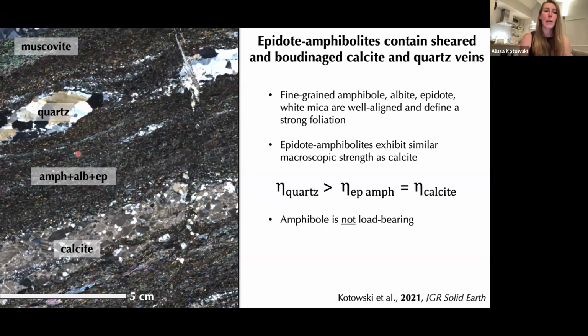So the epidote amphibolite matrix here, we can see that it's exhibiting a similar macroscopic strength to this calcite vein, but it's weaker than this quartz, which is being boudinaged within this foliation. So this allows us to put a bit of a bracket on how strong or weak these epidote amphibolites really are. And in fact, the fact that they're showing very similar macroscopic strength as the calcite tells us that these things are actually extremely weak, because we know calcite to be quite a weak mineral, especially in a relatively wet environment like we have here. So in this case, amphibole is not a load-bearing mineral.